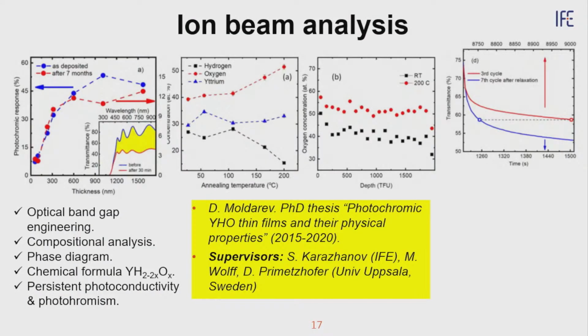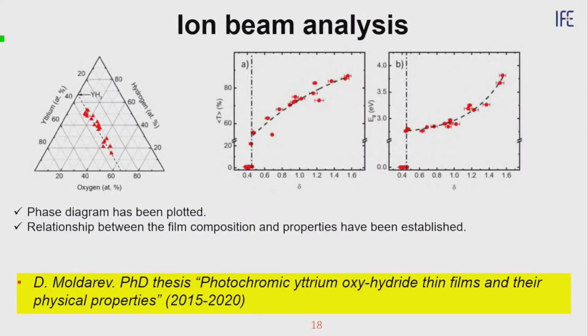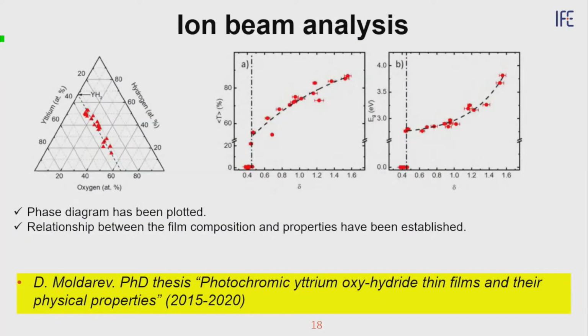Ion beam analysis, we did it in the University of Uppsala: RBS, ERDA, and NRA, and that was the topic for the Ph.D. thesis of Dmitry Moldarev. And so then we showed that the initial postulate is correct. Though by ion beam analysis, we plotted a phase diagram. We have established the relationship between material composition and material property. And then also we have established environmental sensitivity of this material, and that the material will degrade with time, and we should do something with that.